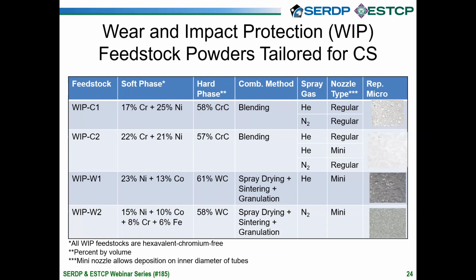And we also had the WIP W1 and W2 powders, which are tungsten carbide based and are produced by spray drying, sintering, and granulation. All the powders are hexchrome free. All these WIP powders have a volume percent of hard phase that is over 50%. And yet we were still able to produce very dense cold spray coatings with these materials. And having that hard phase volume percent so high was important because that gives us the hardness that we need from the bulk deposit.